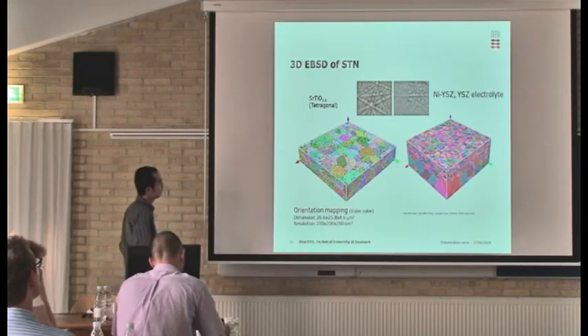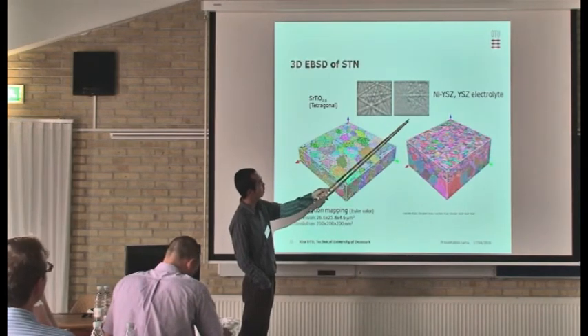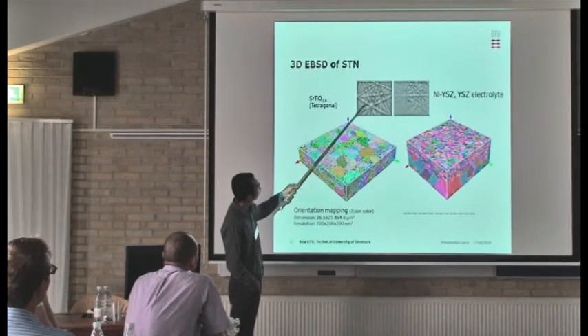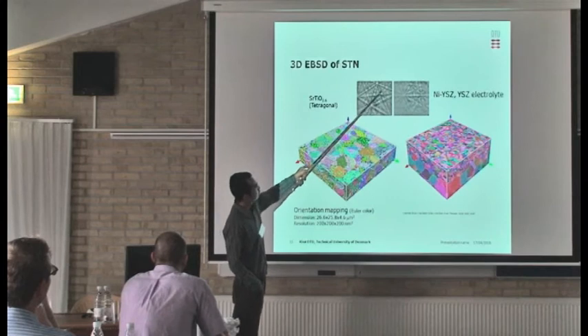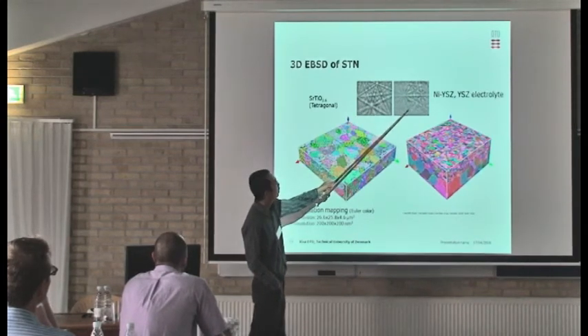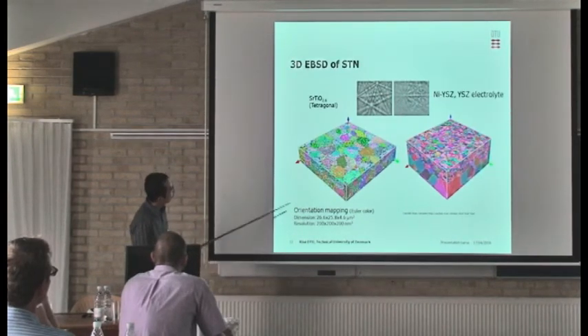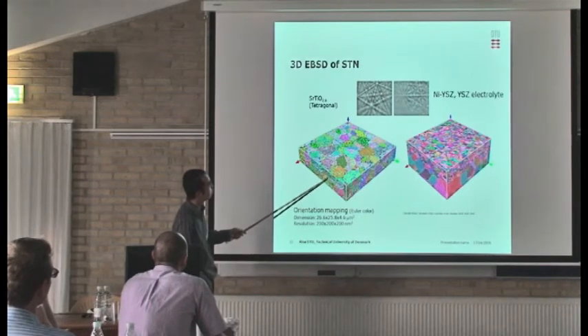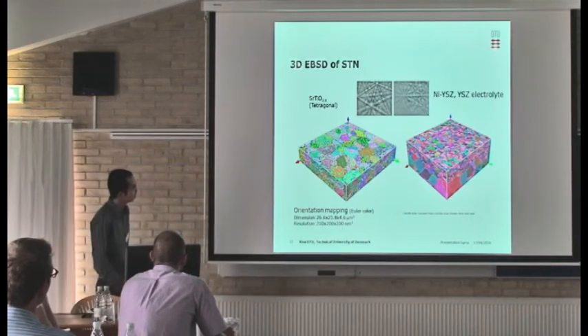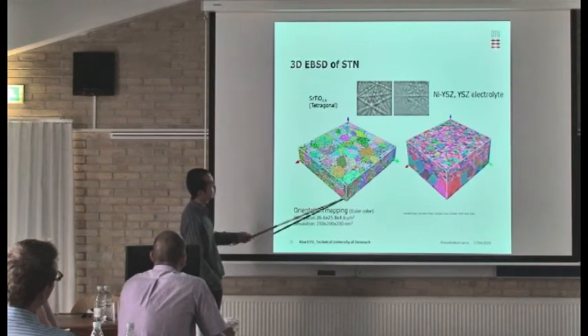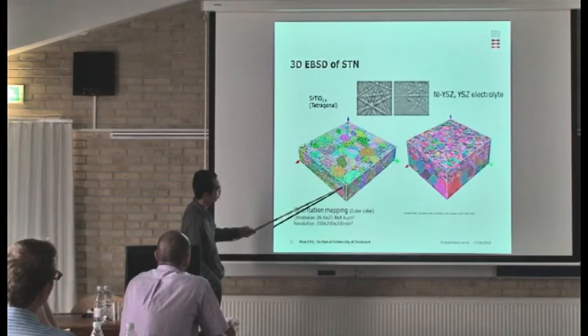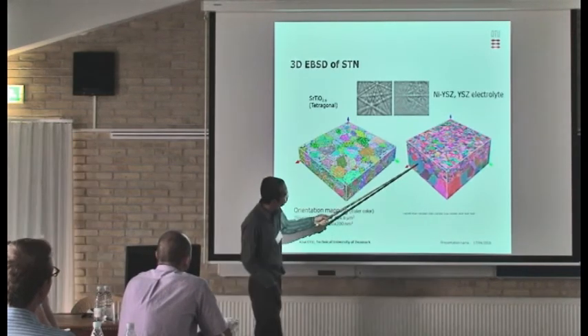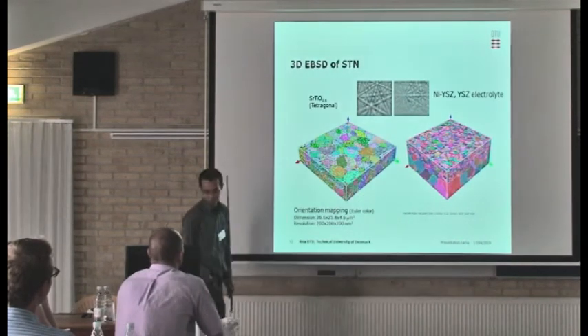Comparing between the two datasets I have acquired, and also comparing the diffraction patterns of these two datasets — from the diffraction pattern, this sample gives a better pattern. But if you look at the other dataset, there is a lot of noise. This noise is a systematic noise that comes from the pseudo-symmetry of the tetragonal structure, and there is also random noise because the pattern quality is not good.